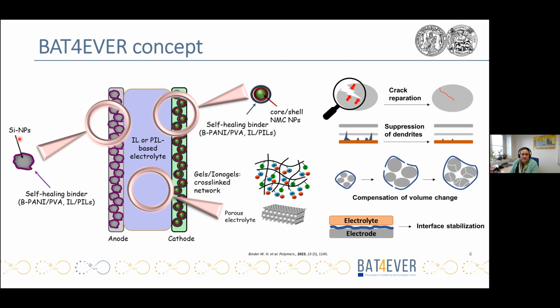On the other side, we are working on the design of novel self-healing polymer electrolytes, which are able to autonomously repair the micro cracks during the battery cycling, while simultaneously suppressing the lithium dendrite formation and stabilizing the electrolyte interface in the battery.